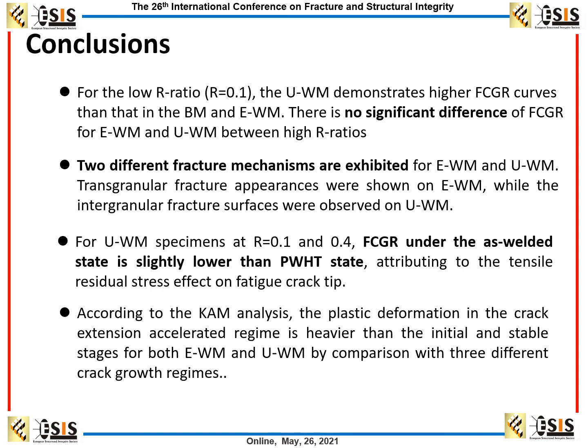The second one is that two different fracture mechanisms are exhibited for the weldments. The transgranular fracture appearances were shown on even matched weldment, while the intergranular fracture surface was observed on the undermatched weldment. The third is the FCGR under the as-welded state is slightly lower than the PWHT state, attributed to the tensile residual stress effect on the fatigue crack tip.